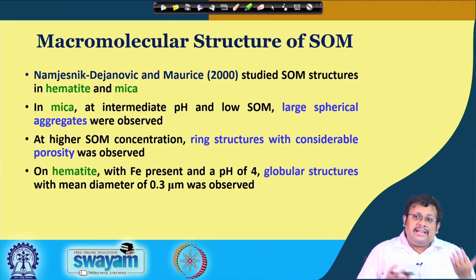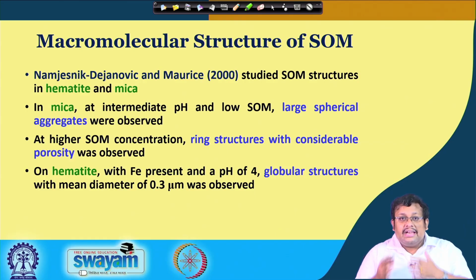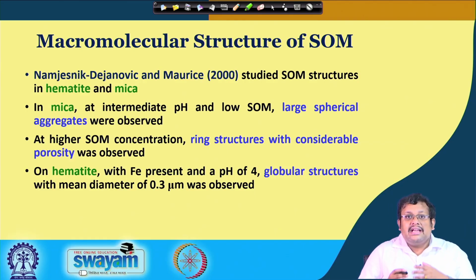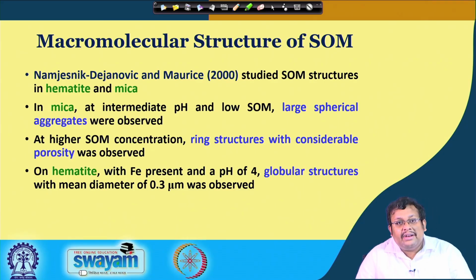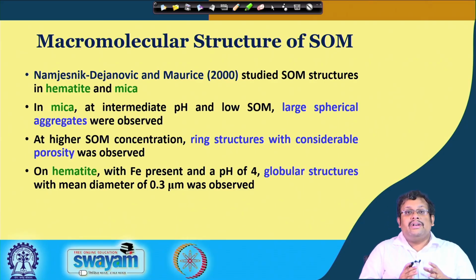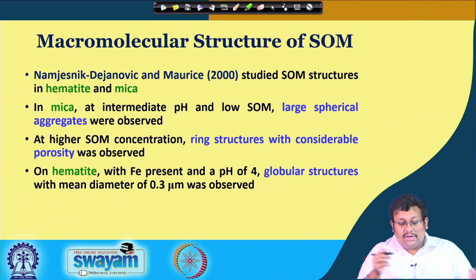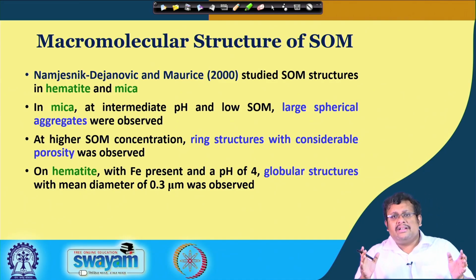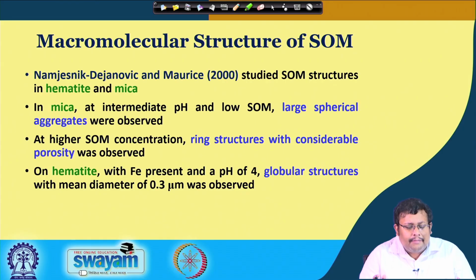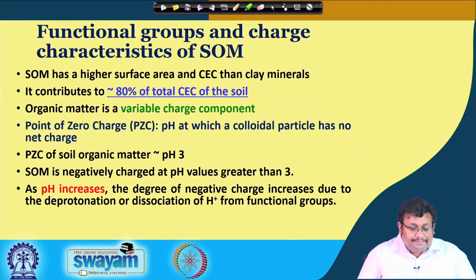On the other hand, in the case of hematite with iron present and a pH of 4, a globular structure with a mean diameter of 0.3 micrometer was observed. So, you can see lots of different structural research has been executed so far, and scientists have produced lots of information on their macromolecular structures.